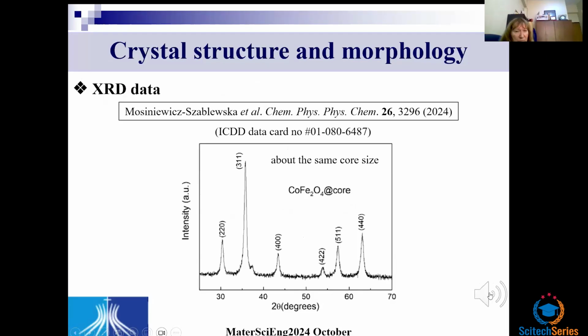This slide shows the crystal structure of the core nanoparticles. So the X-ray data show that the core of the precipitated nanoparticles is exactly the expected structure of cobalt ferrite. So we recorded X-ray data from all of the samples with different surface coating, and they show the same X-ray spectra, meaning that the core phase is preserved in the process of surface coating.